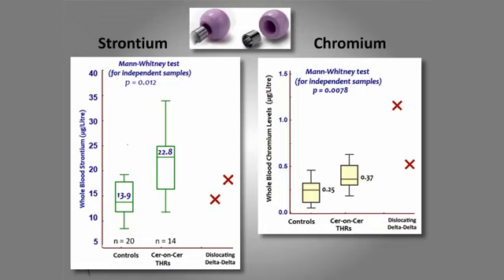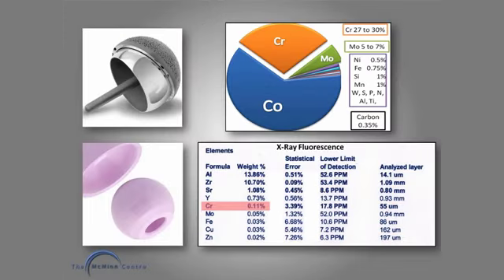And that is quite extraordinary, because the chromium concentration in a cobalt chrome metal-on-metal joint is about 30%, but the chromium content in delta ceramic is around 0.11%. So there's about 300 times less chromium in a delta-delta joint than there is in a metal-metal joint. But still, we have seen an equivalent blood chromium level. How come? The ceramic chemists tell me that this is all to do with bioavailability.